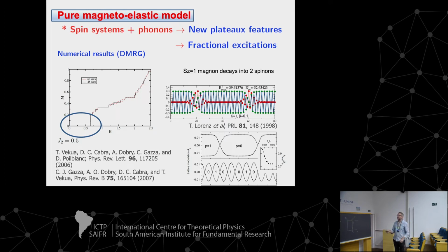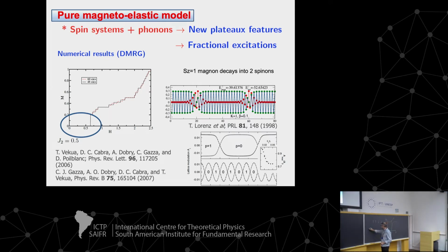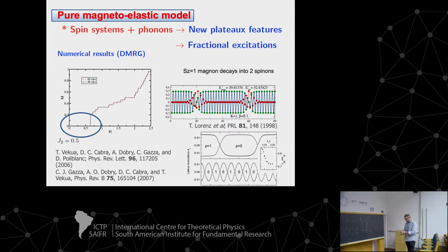So for example, this is the simplest case. Here you have the magnetization as a function of the field. You have a spin gap, so a magnetization plateau, like here, and the magnetization will grow in some way after you overpass this spin gap. And this is what happens in the excited state. So I will draw a cartoon here. In the zero magnetization situation, you have classically something like this, which is not true in this case, but for the ideas I want to discuss, the picture is similar. Of course you can have this guy or this guy, so you have two possibilities for the ground state, either these or singlets on the shorter bonds.